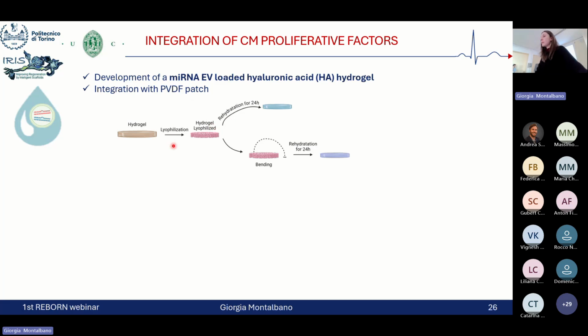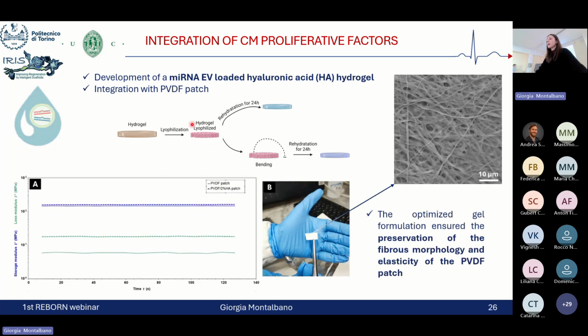So I won't give you all the details about this work, but just the main achievements that led us to the successful integration with the final polymeric patch. So here, the strategy involved different steps where the hyaluronic acid hydrogel concentration was optimized, and then the overall polymeric formulation was adapted in order to better combine with the fibrous polymeric matrix that was then lyophilized in order to obtain a matrix that would be flexible and stable over time, for the long storage of our device. And as you can see from the images, the optimized formulation proved to preserve all the fibrous morphology of the final patch, as well as the overall elasticity.